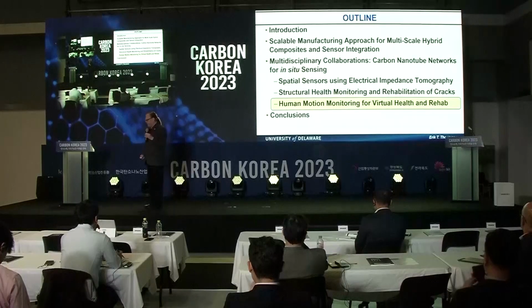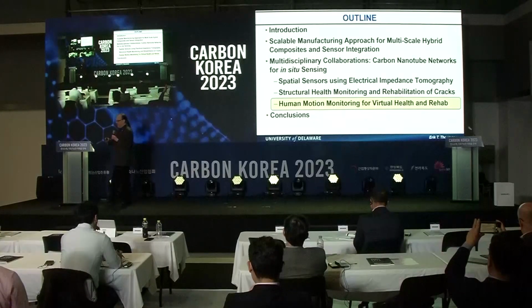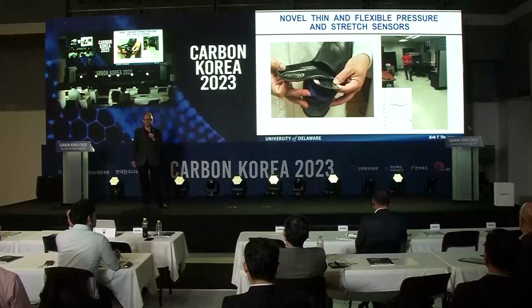So this last part, that I want to spend about the last 10 minutes talking about, is an exciting area that we've moved into, in particular, utilizing these sensors and taking them in a new direction. Previously, almost all of our sensing was done where you embed the sensor in a composite or disperse the nanomaterial in the polymer matrix. But in this case, the coating is actually very soft, even though the nanotubes are quite rigid, it's almost like a sponge. So it's soft to the touch, but it's very well bonded to the surface of the fiber through the chemistry. And so we were able to coat a wide range of materials, and we developed some unique sensors.